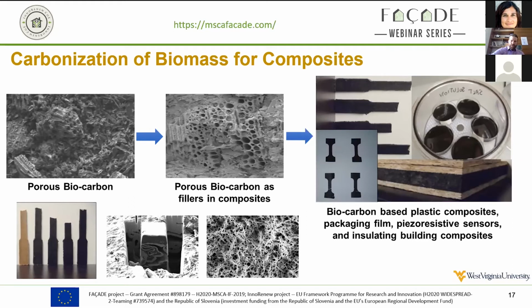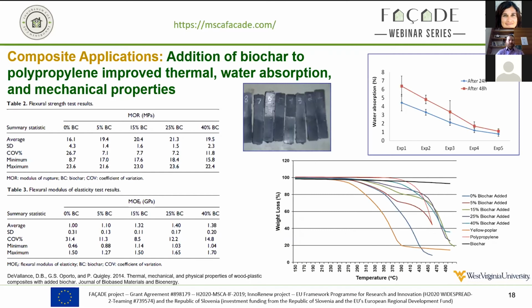So I have a couple slides that I'll go through here on using this for composites. I have some examples of mixing this with polymers to make films, to make insulating materials, to make wood plastic composites. Here was research that we did looking at adding different levels of biochar to polypropylene. In this case, we were able to improve the thermal properties, the water absorption properties, and mechanical properties. In tables 2 and 3, you can see generally as you add up to 25% biochar, your bending strength increased. Same thing with the elasticity. You actually ended up getting higher MOE values by adding this biochar in.